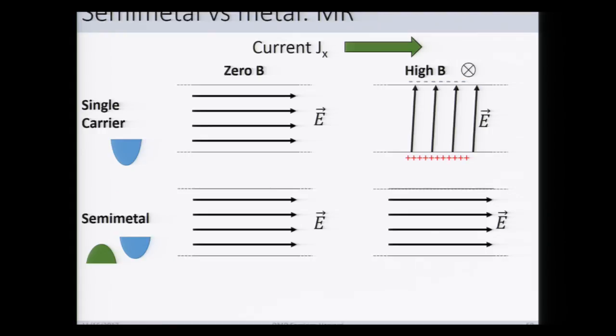And this magnetic field gives you a Lorentz force, which causes electrons to pile up at the top and bottom of the channel, and gives you a Hall electric field that at very high magnetic fields can actually dominate the electric field profile of your sample. In the case of a semi-metal, at high magnetic fields, you get both electrons and holes piling up on opposite ends, and if at exact compensation, these cancel out, and you can imagine that the electric field profile is actually the same as it was at zero magnetic field.